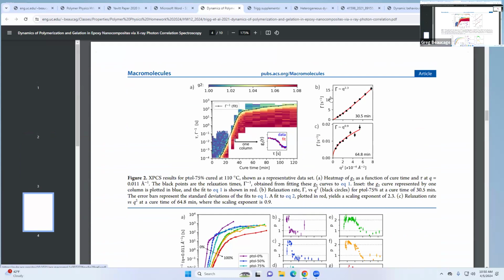Oh, so this is what's interesting. Now they're plotting that relaxation rate as a function of cure time. Each one of these columns here is basically one of those slices that I showed in my plot there. So if you were to zoom in, that one column would be one correlation function where they could fit that relaxation rate. So they're seeing, again, as they cure this sample, that relaxation time is increasing and the thing is actually curing. But if you go in and look at the Q dependence in this regime down here, you get this type of behavior.